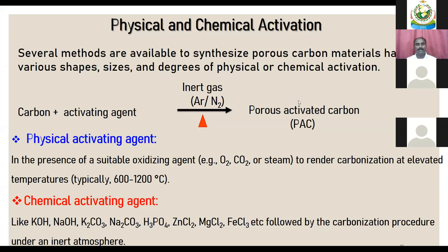So this carbon contains a high surface area, high porosity, and high pore volume. Chemical activation agents are nothing but our laboratory reagents, like potassium hydroxide, sodium hydroxide, potassium carbonate, sodium carbonate, zinc chloride, magnesium chloride, and iron chloride. These salts are mixed in an appropriate ratio with our carbon material, followed by a carbonization procedure in an inert atmosphere at high temperature, like 600 to 1200 degrees centigrade. We get the highly porous carbon. So this porous carbon material is now ready for further applications.